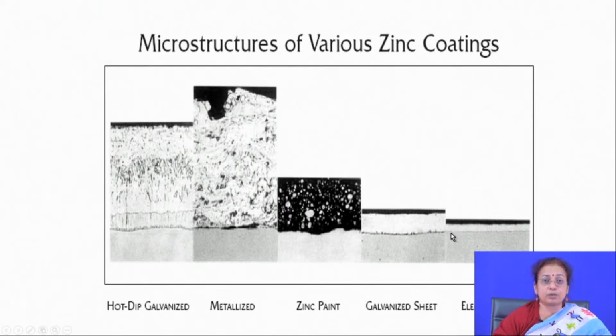Now, another parallel route by which you can do zinc coating is the electro deposition process. Here the thickness is a major trouble. You cannot go beyond a certain thickness, maybe 20 to 25 micron is the maximum thickness that you can achieve when you go for electro deposition, and the interface is also not so strong. So if you talk about different parallel techniques, you will find that so many techniques are available. Depending on the applications, you have to look for the technique which you should opt for.